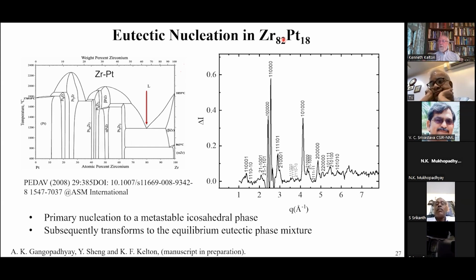There's been a little bit of work on eutectic formation, but there you find out that you get different answers depending on which papers you read. One paper might argue that, based on the experiments, there's nucleation of a metastable phase first, which then subsequently transforms to the eutectic phase mixture. Another paper might argue that you nucleate one of the two phases of the eutectic, and then that catalyzes the other. But there's really no clear evidence of any of that.